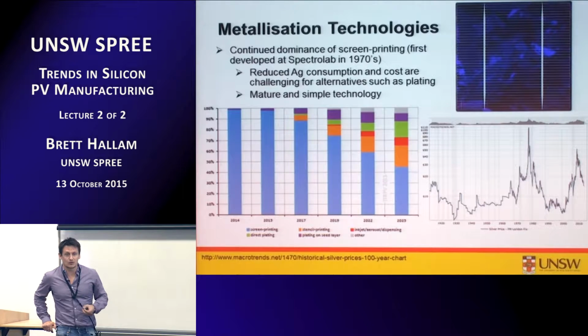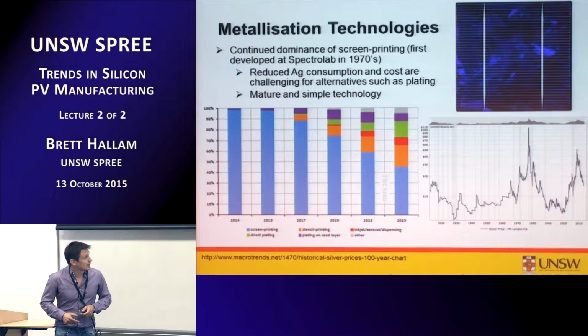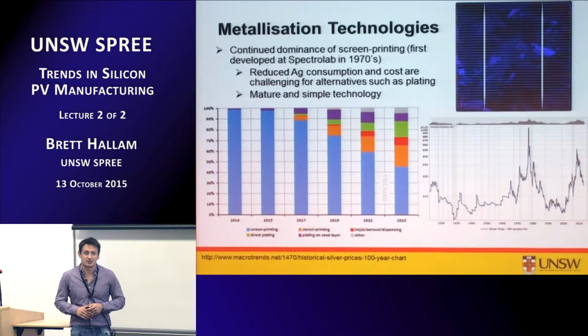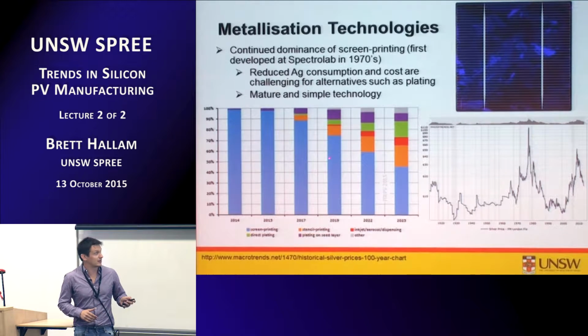So those few years ago was when plating certainly looked exciting, because it could potentially be a lot cheaper by completely eliminating the silver on the front surface, going to a copper-based conductor, using some of the plating technologies we've developed here. Unfortunately, once the silver price comes down, the financial advantages of shifting away from screen printing to alternative technologies like plating, where they can use copper as the main conductor, have pretty much gone. So really the industry is not looking like it's going to have any significant portion of plating and these other base technologies. Certainly in the next, say, 5 years, it's going to be heavily dominated by screen printing.